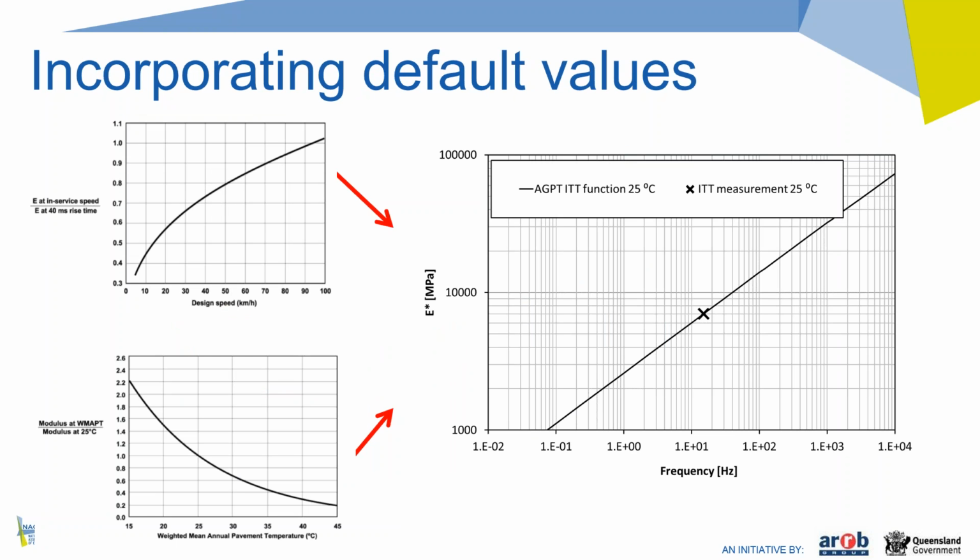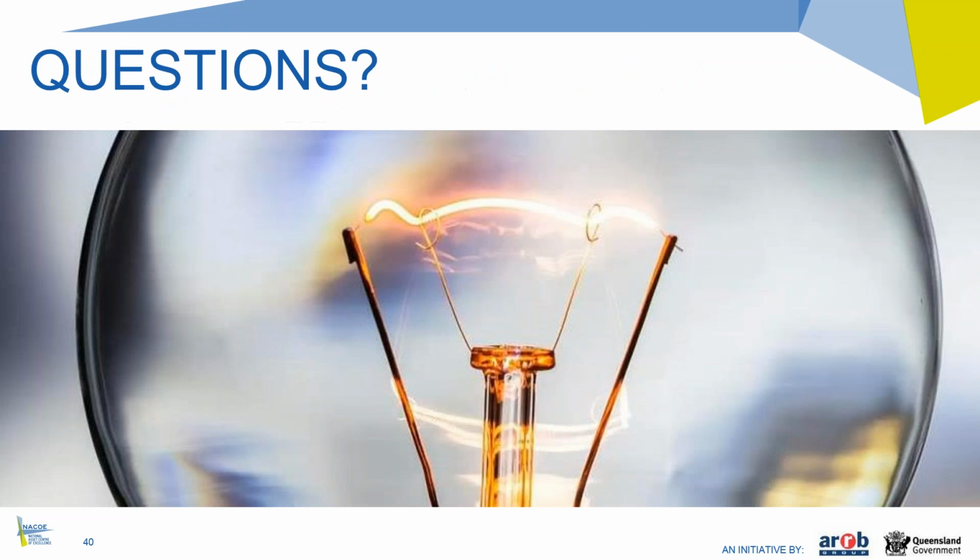Actually show that bottom asymptote as well. So we haven't cut off the 1000 MPa in that example. So when we send out the technical note, you'll be able to look at one of the figures in there just to see exactly what Eric's saying about the asymptote being symmetric at both ends. Yeah, I guess to answer David's question a little bit further, the asymptote is typically between 200 and 500 MPa if you're doing laboratory testing.